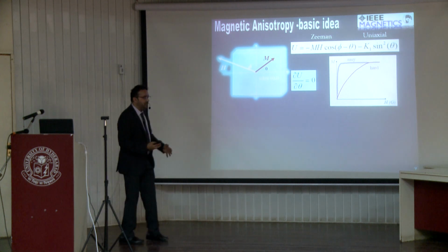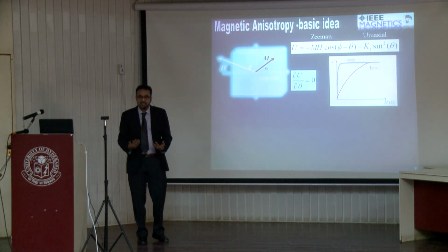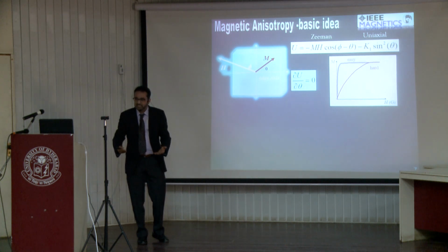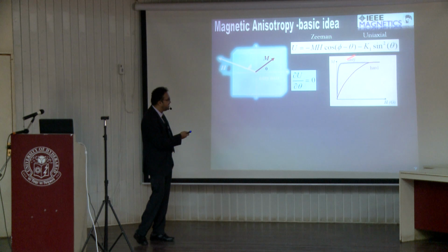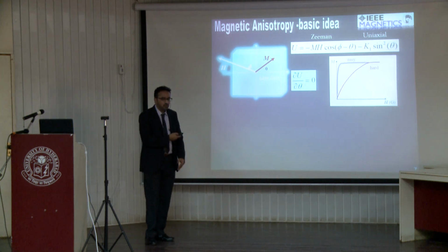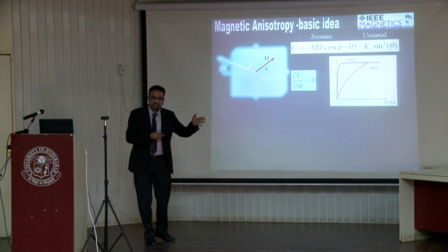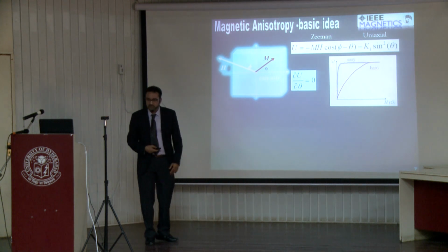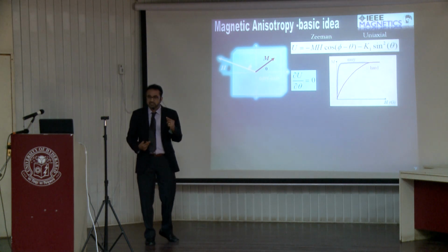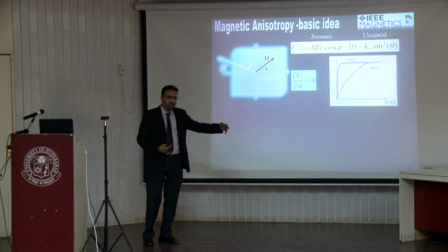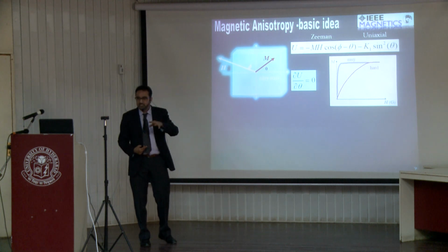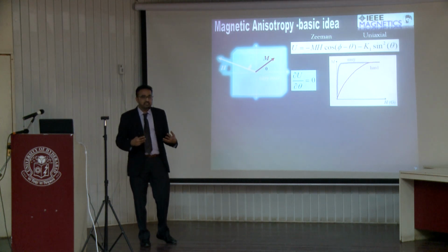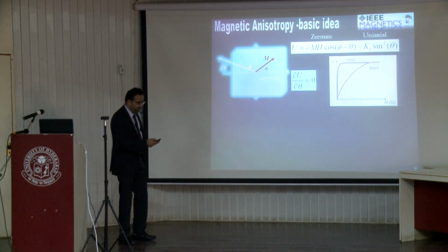And in fact, because of this intrinsic energy that the magnet has, which is determined typically by certain directions where it is easy to magnetize, for example, we call this the easy axis and the hard axis. And depending on how you apply the magnetic field with respect to the internal preferred direction, the shape of the hysteresis loop, or the MH curve, is different. This is key to today's talk, because we're going to use this possibility of tuning the shape of the hysteresis loop for increasing the figure of merit for this particular application, namely hyperthermia.